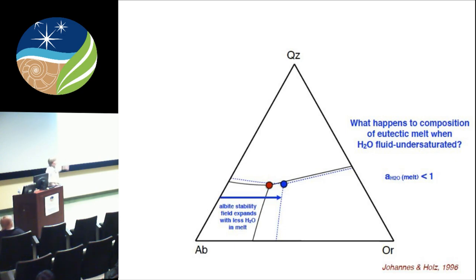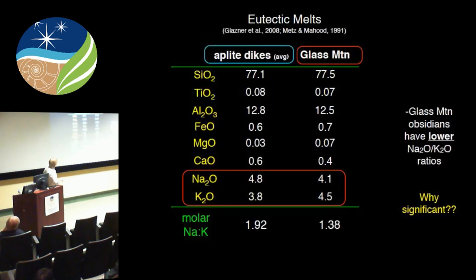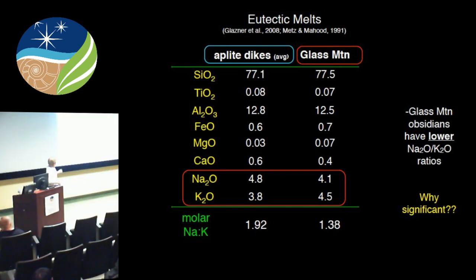So what that means is that if a melt is extracted from a quartz, plagioclase, orthoclase-bearing assemblage, whether the magma is crystallizing or partially melting, if it's water undersaturated, the composition should have a higher potassium to sodium ratio. Well, we see that. Glass Mountain has a lower sodium to potassium ratio, more potassium, less sodium than the aplite dikes. But more than that, if it's born at this depth, what then is going to happen?